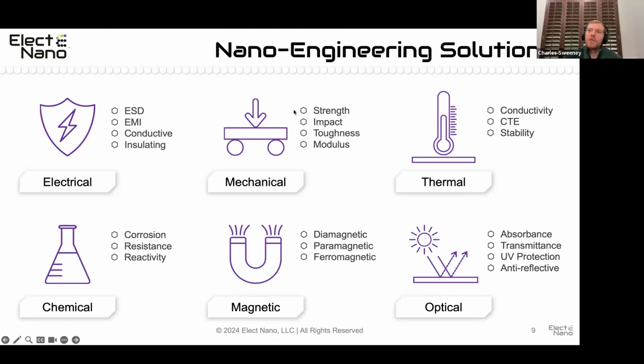Yeah, and typically you would want to get a little bit more clever in terms of how you engineer that interface. With stealth applications, I wouldn't want to go too deep into it, but you have an incident electromagnetic wave. Even if that hits a perfect dielectric, some of it's going to get bounced back because the propagation in free space is not going to match when you change dielectric constants. And so the name of the game usually with stealth applications is you want to match the dielectric constant of air or whatever medium it's going to be in as closely as possible, and then have a continuous gradient where you're transitioning slowly into your maximum absorption material.